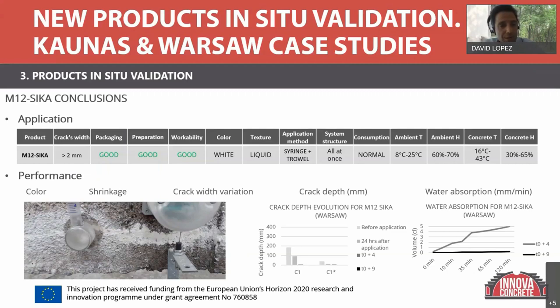Related with the performance monitoring, just to mention that here we checked mainly color, shrinkage, crack width variation with the device of continuous monitoring that I mentioned before, installed by Rina, and the crack depth using ultrasonic pulse velocity and water absorption.